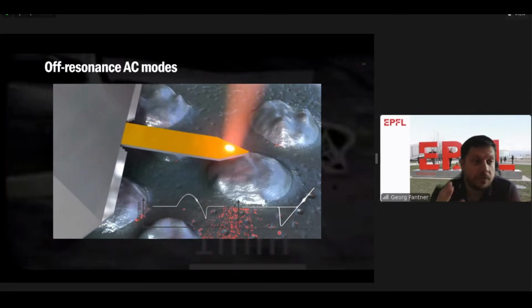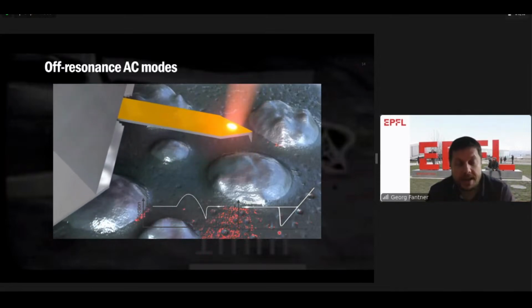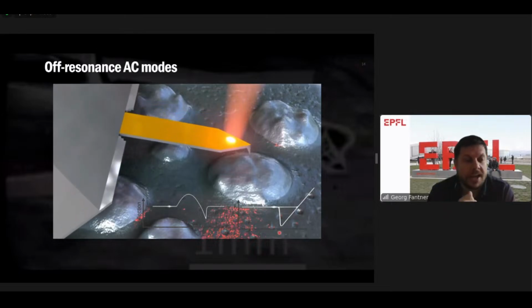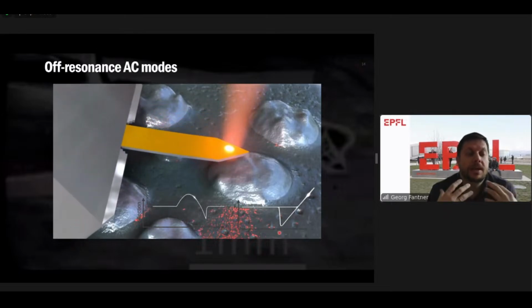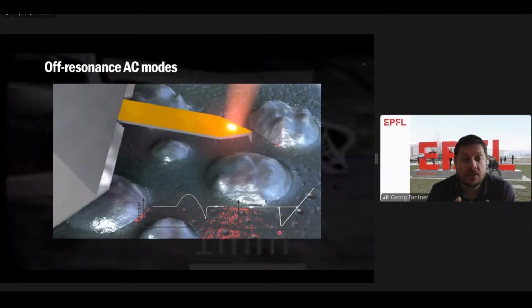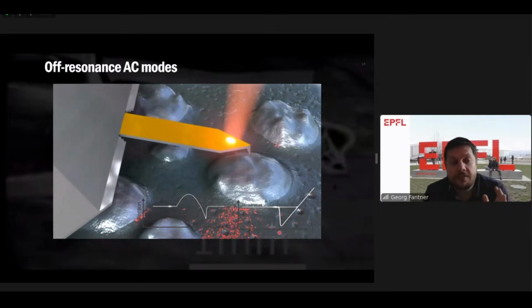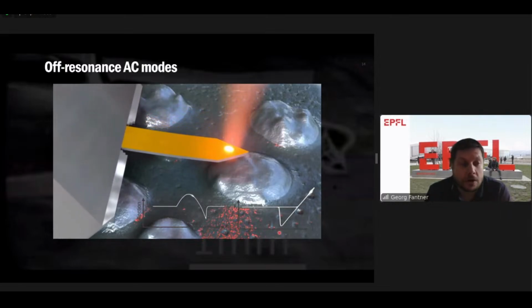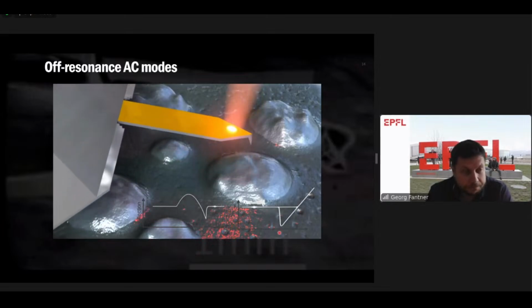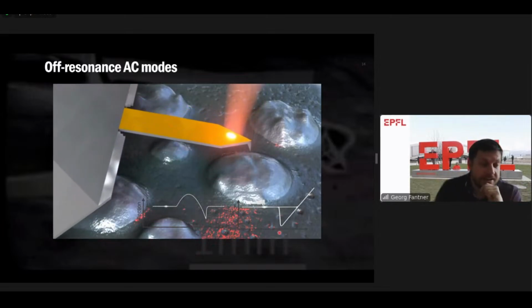Now, the issue here is that this motion of the cantilever up and down happens with a piezo actuator. And you have to move either the whole sample up and down or the whole cantilever up and down. And you're moving really a lot of mass, which really slows it down. So off-resonance AFM modes tend to be even slower than tapping mode is. So it's not really helping us in that respect.